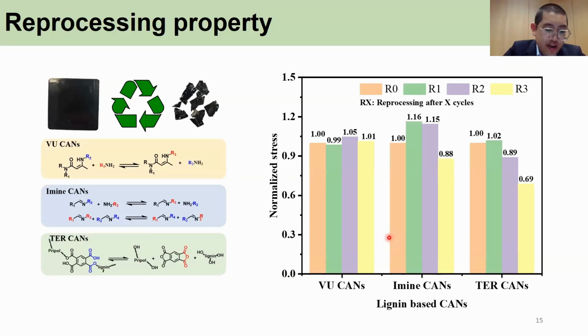Reprocessability of the material is our ultimate goal. We found the vinylogous urethane kinds and the imine kinds show really good reprocessability properties, but the recycling performance of the transesterification kinds drops significantly after the second cycle. This is because of the side reaction. The irreversible bonds lower the recyclability of the material.